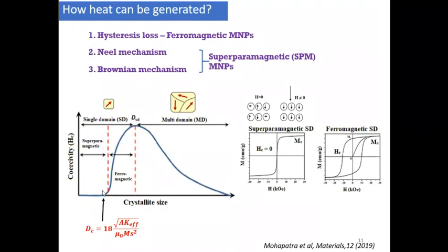The critical diameter where the coercivity is zero depends on several factors. One of the major factors is the saturation magnetization and the effective anisotropy constant. The effective anisotropy constant is due to the shape of the magnetic materials, the crystal orientations, or the magnetocrystalline anisotropy of the material. As the saturation magnetization and anisotropy constants are different for different types of materials, the critical diameter is also different for different materials.